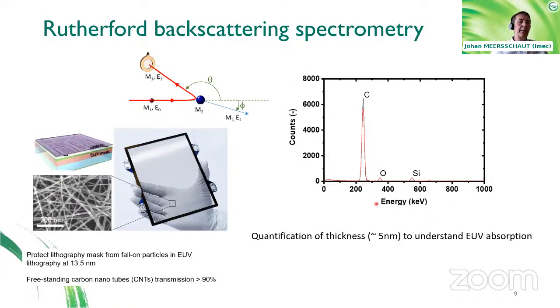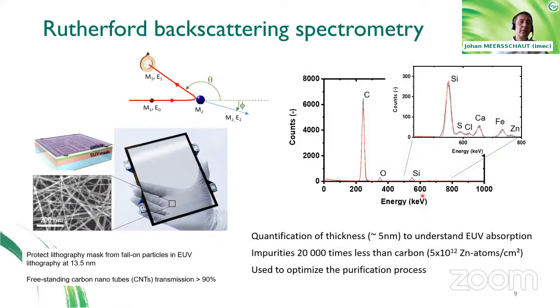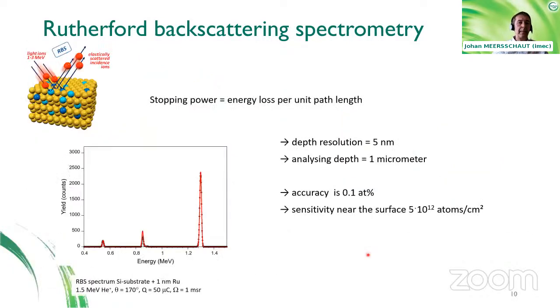On the other hand, you also see that due to the fabrication, there is some contamination in this material. And it's very important to understand which kind of contamination and how much of that contamination is present in the sample. And you see that with RBS, with Rutherford backscattering spectrometry, we are very sensitive to even minute amounts of contamination in such a pellicle. The impurities of, for example, zinc are of the order of 20,000 times less than the thickness of the carbon. And still, we are able to quantify these materials. So this technique is very supportive in the further development of these pellicles that are being used for practical applications.